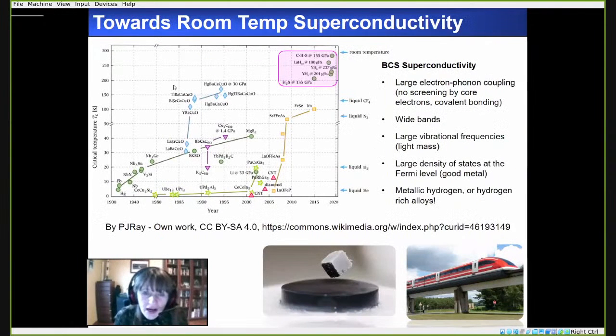One of the places where high pressure has been shown to have revolutionary advancements is in the area of searching for room temperature superconductivity. So here I show the TC, superconducting critical temperature, versus the time. And as you can see, we have a steady increase in TC with the high temperature oxide revolution in the 90s shown right here. However, after that, the TC did not increase for quite a long time until we see this nice increase in the pink cells. And these revolutions right here occurred because of the high pressure research.